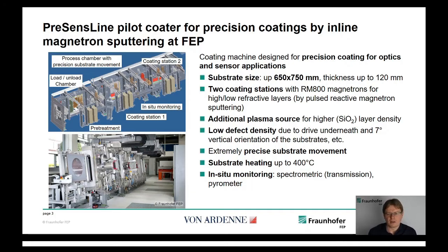So here are some features of the machine. It's a machine that is mainly dedicated for precision optical coatings and coatings for sensor applications. The substrate size is up to 650 times 750 millimeters, thickness up to 120 millimeters. We have two coating stations, and when we deposit optical layer systems, one is for the low index material and one is for the high refractive index material. We have an additional plasma source that we need for the silicon oxide process to get a higher layer density.